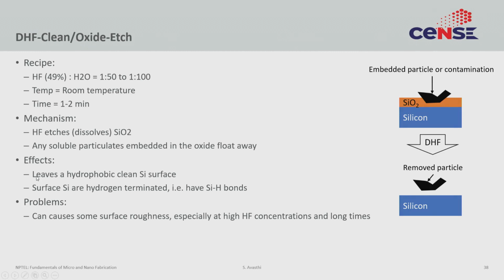Certain side effects, it does leave a hydrophobic surface. What hydrophobic means, the water does not stick to it. So once you take the wafer out, you will actually see no droplets on it because it's completely clean, the water is not sticking to it. That's a sign that your etch has completed and you should take the wafer out. Okay. And the other thing is that it passivates the surface of the silicon with silicon hydrogen bonds.